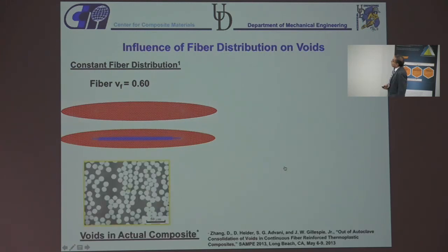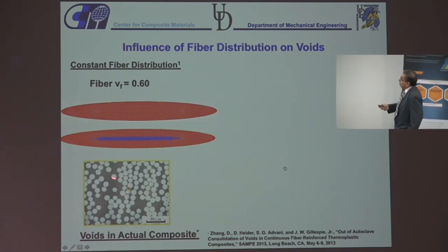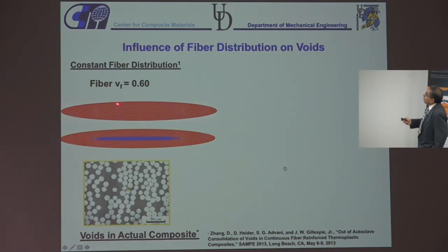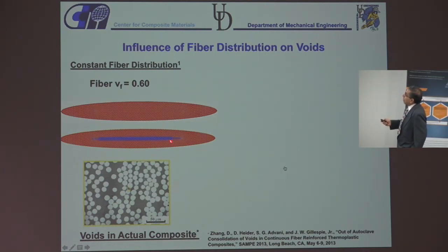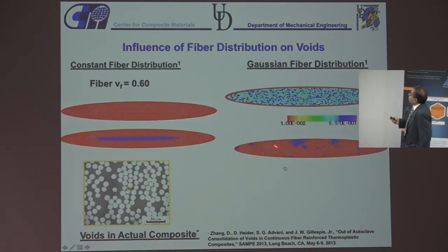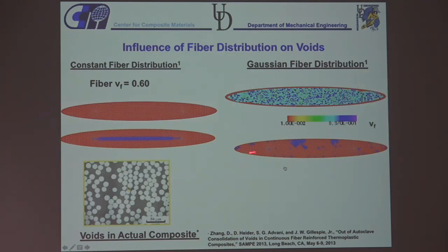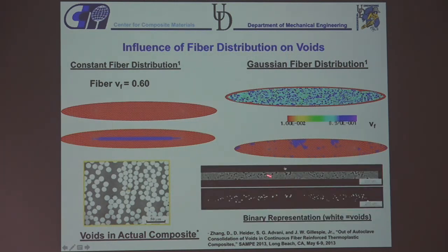And the other thing at this level it can tell you, as I said, these fibers are kind of separated not uniformly. So the capillary pressure is going to be high here, but not in this region. And if you keep the capillary pressure the same everywhere, or the distance between the fibers the same everywhere, and you introduce the resin from the outside, you'll find that your void, this blue area, is right in the middle. However, if you introduce the capillary pressure, which will be different in different locations, and now this has been denoted here by fiber volume fraction in the toe being different inside the toe, you notice that the voids are not like this, but they are spread out, which is what is observed in practice. The voids are never in the center of the toe. And so this tells you that if you can get the voids to the edge of the toe, you can vacuum them out, and then you can stop it from having voids inside.